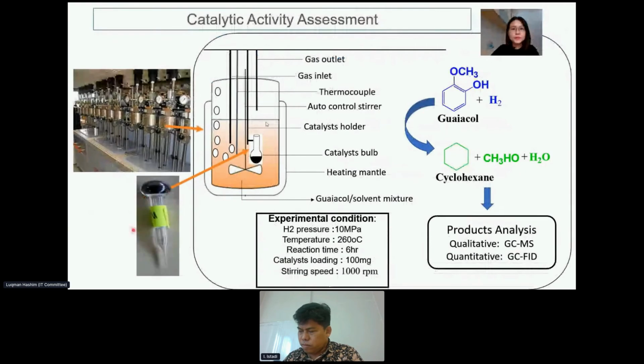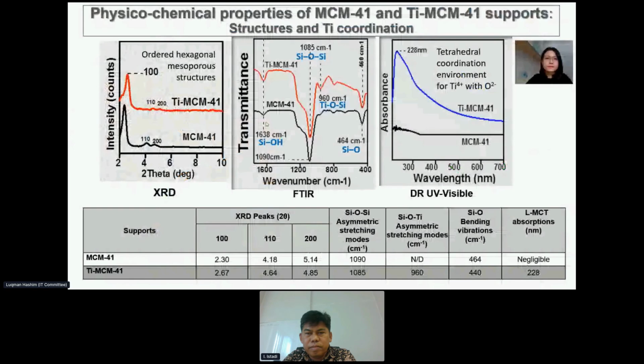The prepared catalyst is first reduced in hydrogen gas at around 550 Celsius for 5 hours, and then the reduced catalyst is kept in a glass bag and sealed before the commencement of the reactions. The hydrodeoxygenation process is conducted in a pressure reactor under these experimental conditions, in the presence of hydrogen gas. The final product is analyzed using GC-FID as well as GC-MS for quantitative and qualitative studies. The physicochemical properties of the modified MCM-41 support as well as the final catalyst will be discussed here. These are the microstructure properties of the MCM-41 support with and without the titanium dopant.